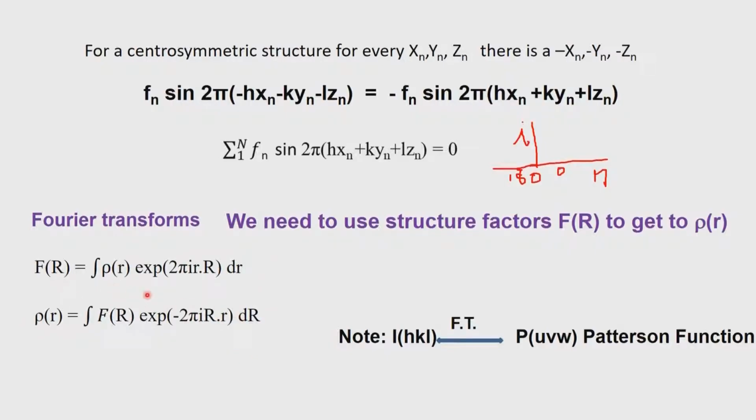So, it is also very clear that once we have got this information about f of r, it is in fact the scattering structure factor, and that structure factor is the square root of the intensity. So, in the typical X-ray experiment, we send in an X-ray beam, get the diffraction done, and we identify the coordinates of each and every spot in the reciprocal lattice in terms of HKL, and we measure the corresponding intensities of HKL with a detector. So, this intensity of HKL will give us the modulus of f of r, but the phase associated with f of r has to be calculated.